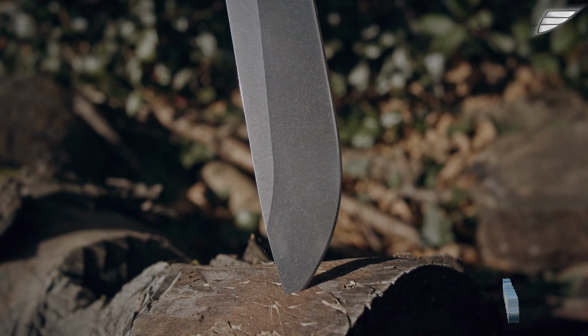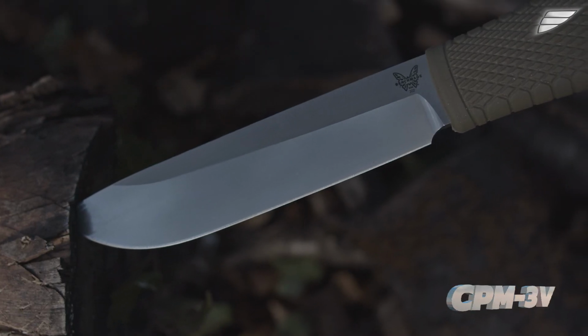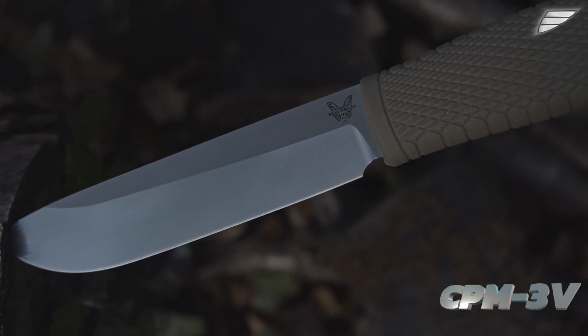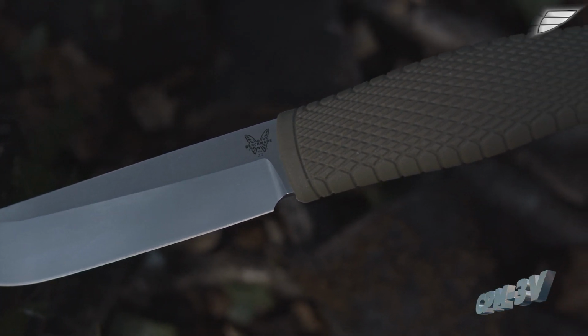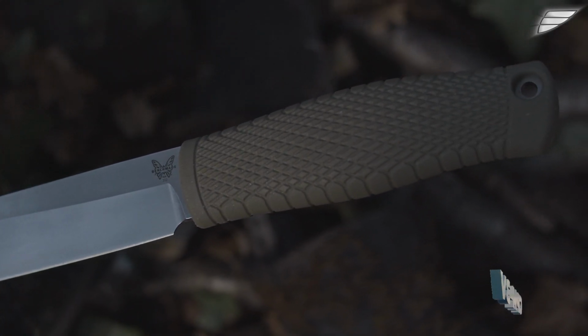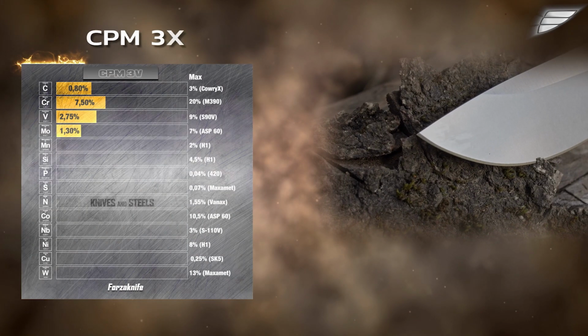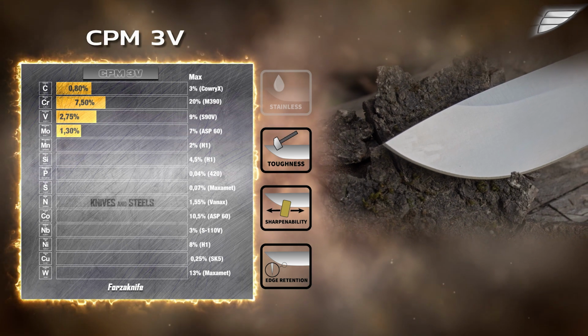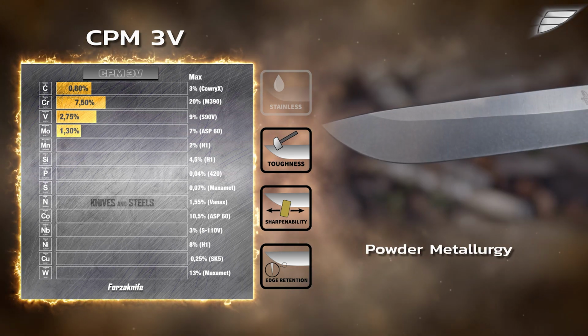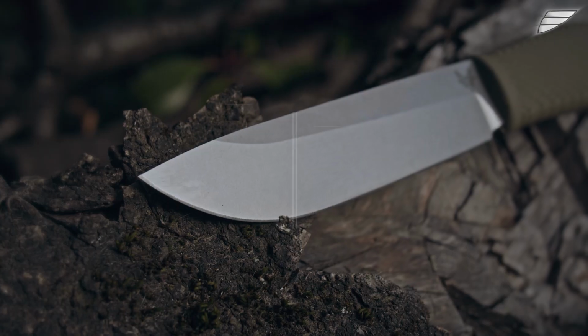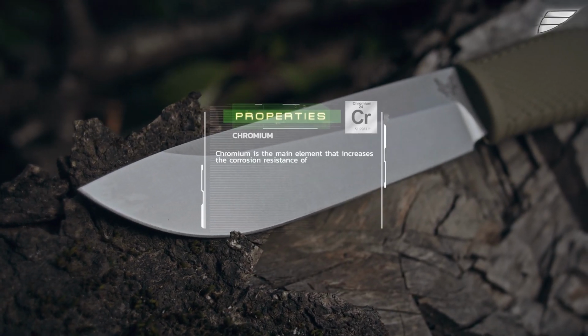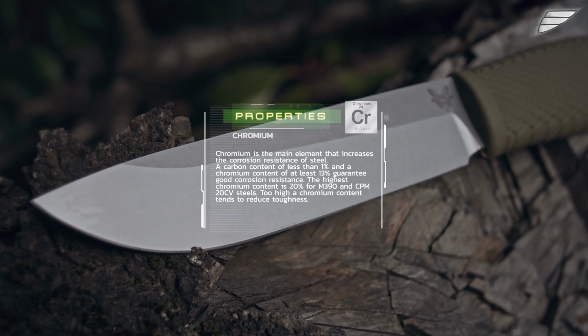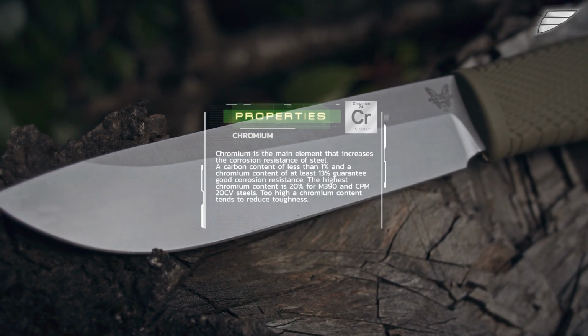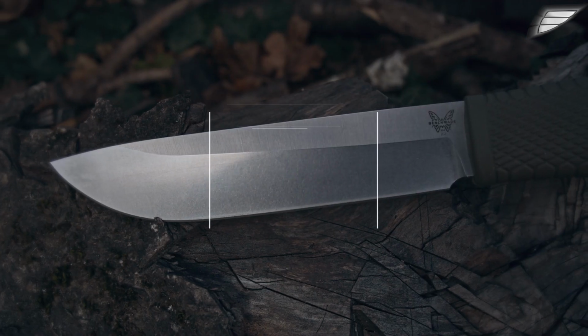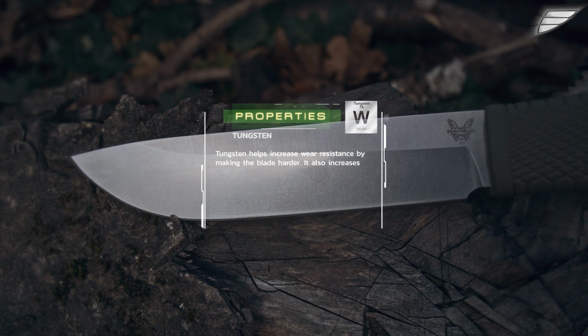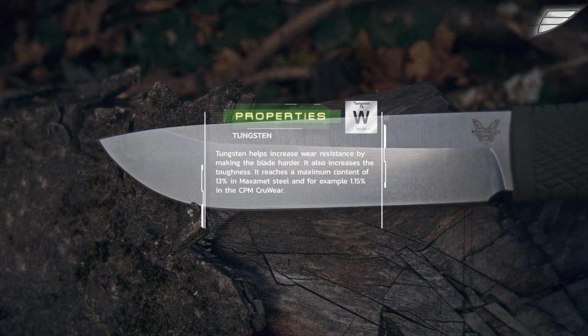Its composition is simple. Official data from the manufacturers reveal that in addition to iron, the alloy contains 0.8% carbon, 2.75% vanadium, 1.3% molybdenum and 7.5% chromium. This chromium content is insufficient to make the CPM3V stainless, but it is however not too sensitive to rust if care is taken to dry the blade. However, the spectral analysis present on the knife site also reveals the presence of 0.4% tungsten.